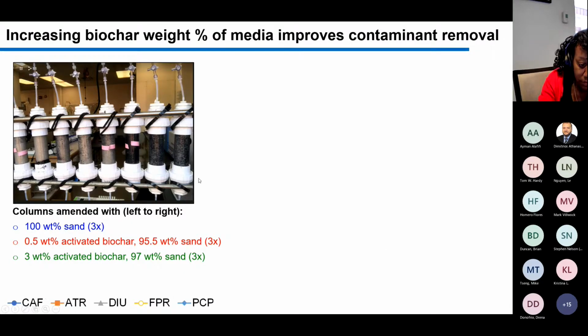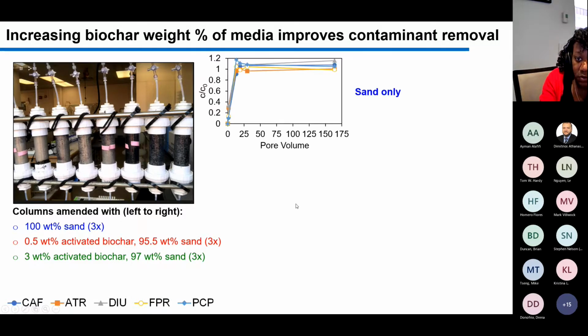So here are the figures I'll show in a second, have the different compounds that we've spiked into this synthetic matrix. And here we're plotting the performance of the columns in terms of pore volume on the x-axis. So one pore volume is the amount of water that could be contained in our columns in their packed configuration. So packed, again, with either sand or biochar. So the more pore volumes that are treated, the more volume of water has passed through your column. And then on the y-axis, we're plotting normalized contaminant removal. So measured concentration over initial concentration present in the stormwater matrix. So low values means very high removal.